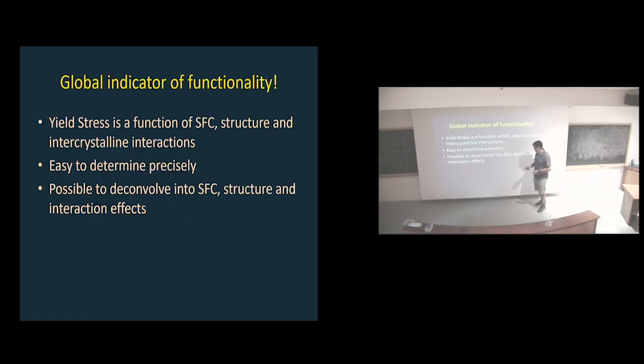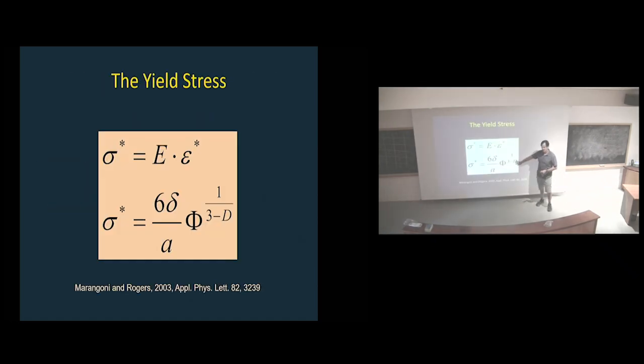But of course, the problem with this treatment is that it's very hard to predict the fractal dimension. So this becomes a fitting parameter. And if I tell you it's 2.5, or 2.3, and it's Monday, it's 2.2, and it's Thursday, it's 2.4, it has a huge effect. So people get less excited about that.